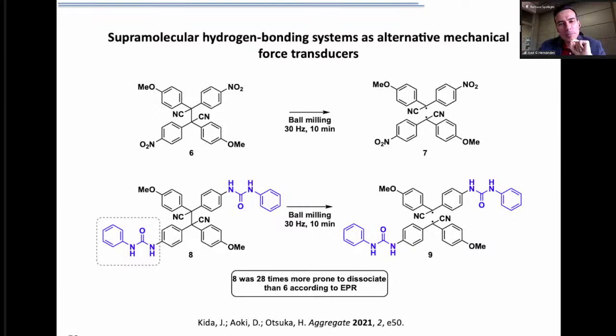And this is another point that I wanted to highlight before finishing, and it is related to the ability of non-covalent interactions such as hydrogen bonding to facilitate the assembling of small parts together so that you can create something like a polymeric material which is kept together only by non-covalent interactions. So here on the top, we have a molecule, number 6, which is a tetraaryl succinonitrile derivative. It is a mechanophore which tends to break apart. You can promote a homolytic cleavage here to generate radicals. And that happens if you do it by ball milling. So you would be able to generate those radicals.